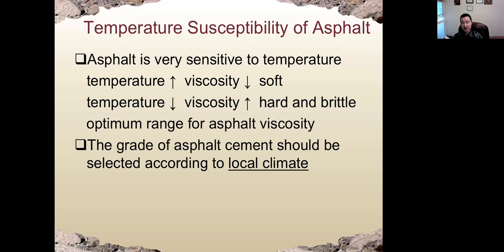So before we talk about the testing method for asphalt, let's talk about the special property of asphalt. Asphalt is a very temperature sensitive material. This is different from Portland cement concrete, which is not very sensitive to temperature. Increasing or reducing the temperature by 20 or 30 degrees will not change the hardening property of concrete quite a lot. But asphalt is very sensitive to temperature. Increase the temperature 10 degrees, the viscosity will be reduced quite a lot, which means it becomes softer. Reduce the temperature, the viscosity will be higher, it becomes hard and more brittle.